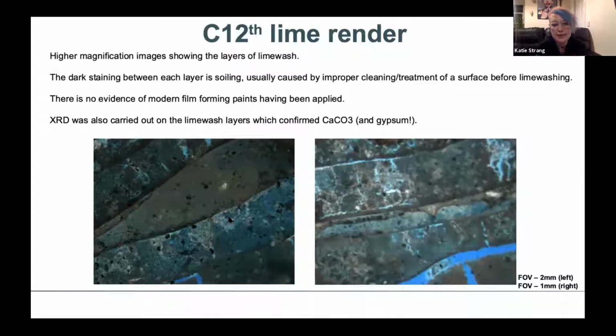The one on the left is 2 millimeters field of view, and this one's 1 millimeter on the right here. And you can see that in between the layers of lime wash are these dark layers, and that's essentially just soiling. It can happen for a number of reasons, but it's normally because the surface hasn't been washed down or prepared properly. Because this had been sitting in a basement and not touched for so long, we don't really know how much work had been done. There wasn't a record because it hadn't been listed since it wasn't actually known about.